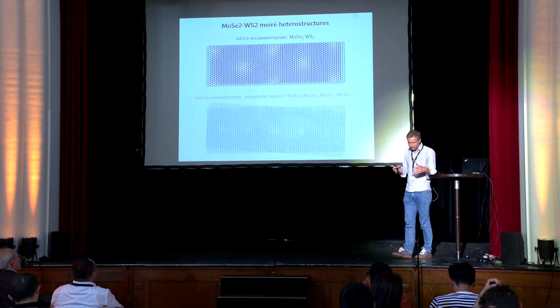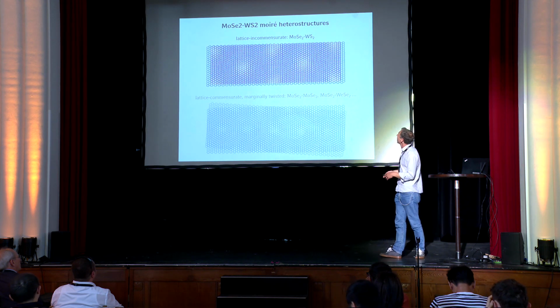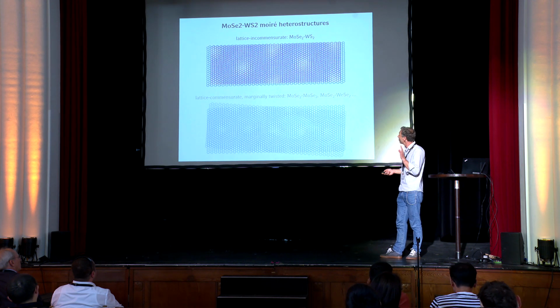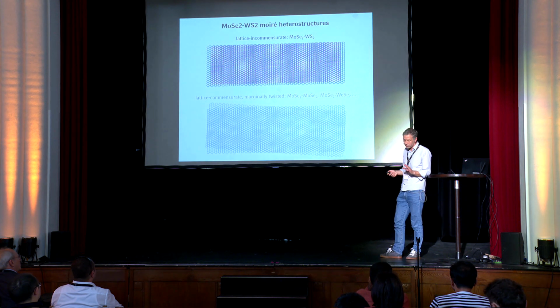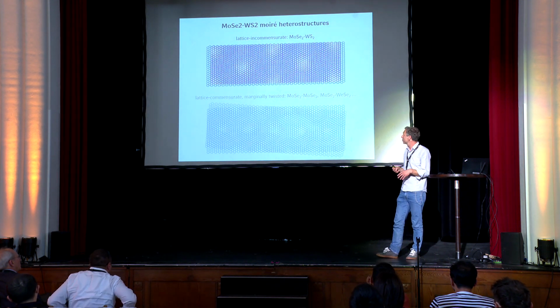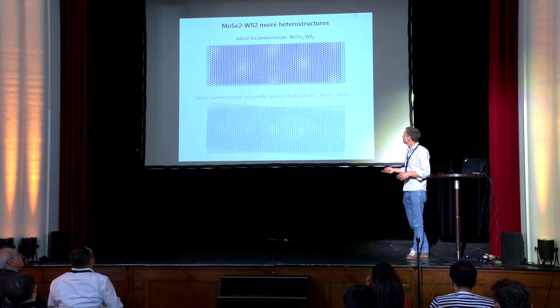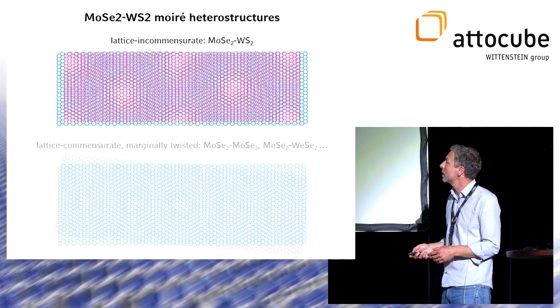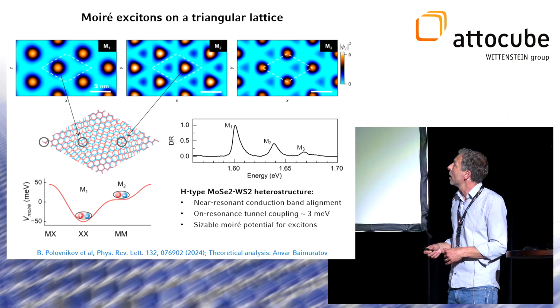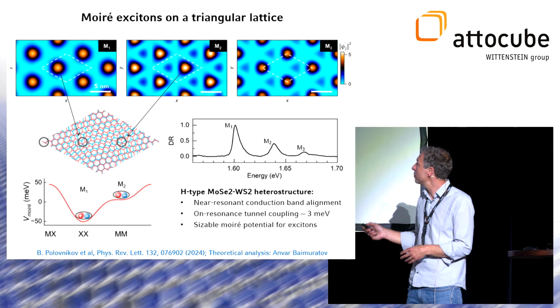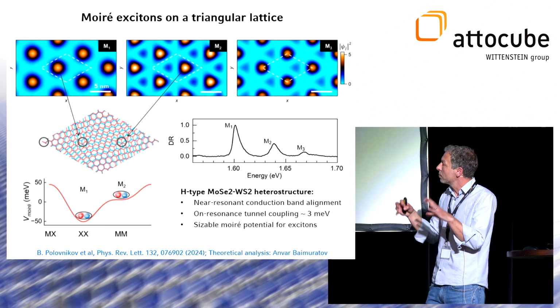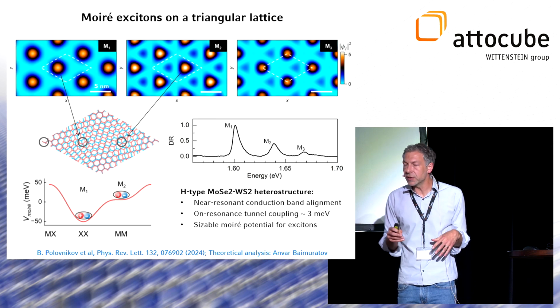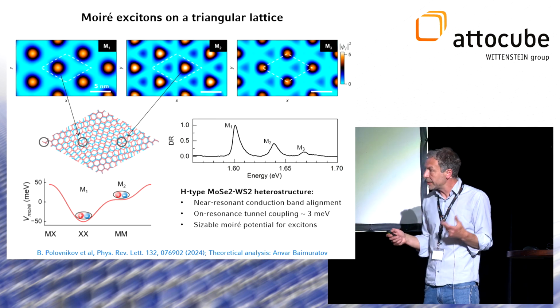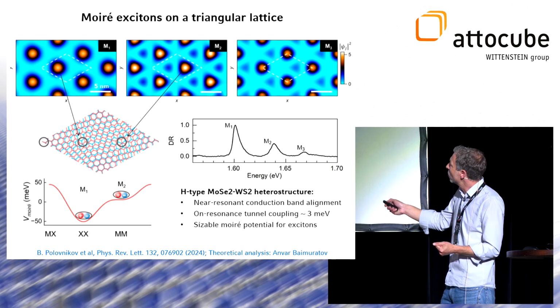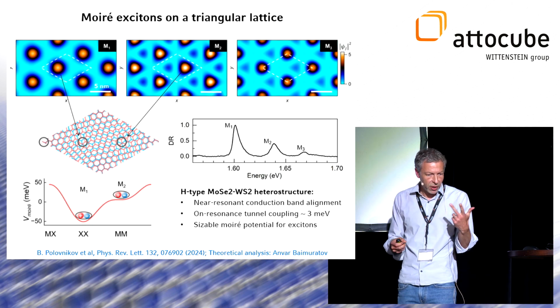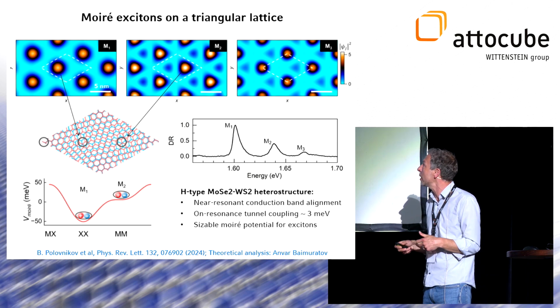In fact, I wanted to build lattices, but I'm running out of time. I would like to note that lattice incommensurate heterobilayers are robust against reconstruction, and this is why they really realize something that is pretty close to our notion of PowerPoint moiré. One example is a molybdenum diselenide tungsten disulfide heterostructure, where according to our theoretical understanding of the system, we have a pretty clear understanding why. Now, in absorption, we observe indeed moiré peaks. There are 3 of them. The multiplicity is due to band folding and hybridization.